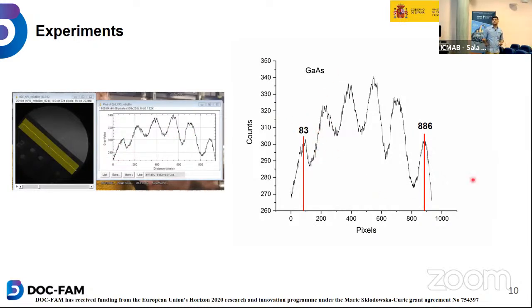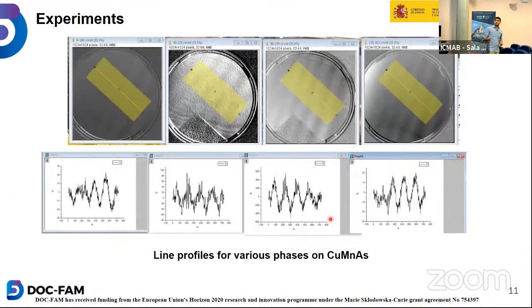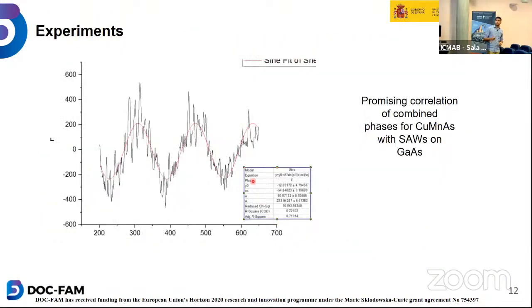The wavelength, which I'm showing here in pixels, is more or less 160 pixels. And then these are the profiles of the antiferromagnetic material on which we draw the line width, at different phases of the wave, at different or the same places. And then we see whether we can see the spin waves in this antiferromagnetic material or not.